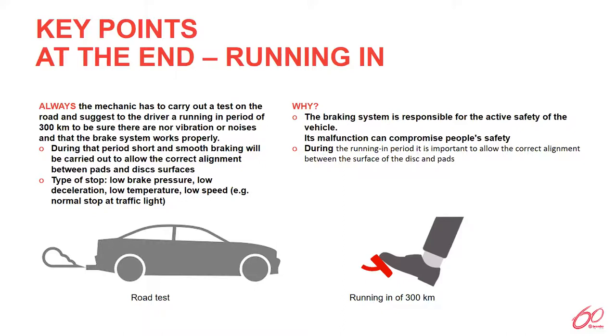But when you hand that vehicle back to the customer, it's essential to advise them as well to brake gradually and to avoid feathering their brakes or heavy braking for about 150 to 200 miles to continue that bedding in process correctly. So bedding in new discs and pads should be done with care to ensure that even material transfer process, because anything that interrupts that process will compromise both braking surfaces and start the foundations of excessive disc thickness variation. So it is advisable to advise your customers that are taking their cars away for their long holidays in August to get their brake service now for this bedding in process to have completed by then.